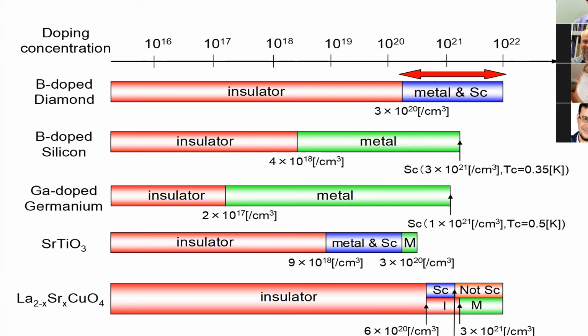One interesting thing is that the optimum concentration of impurities is in these regions in diamond. Some SrTiO3 also shows superconductivity, but the optimum ratio is relatively low. And then a metallic phase, or non-superconducting phase, appears after heavy doping regions. We don't know what's happening, because this is still nearly 10%, but beyond that, what happens, we want to study.